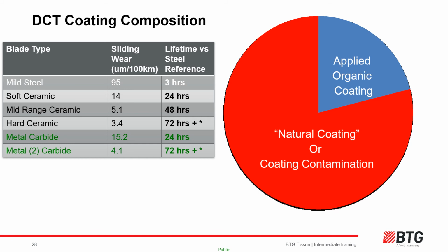Which brings us on to hard coating, the tissue maker's nightmare. Coating needs to be adhesive, tacky and robust to achieve sheet QC specs, and then be flexible and tough in the cured coating layer to protect the Yankee from erosive, corrosive and adhesive wear. Once the coating becomes too hard, the blade stops working in the coating and works against the hard coating layer. Hard coating also makes blades wear faster. Steel will wear faster, of course, than ceramics or carbide blades.